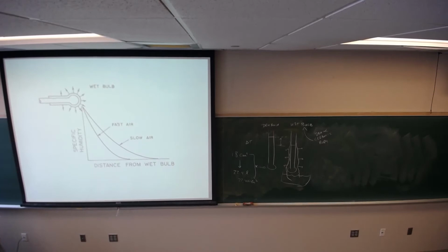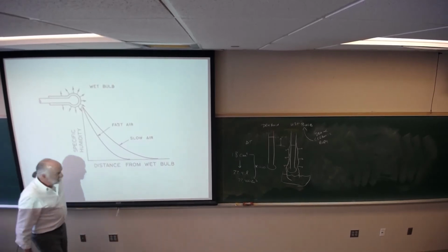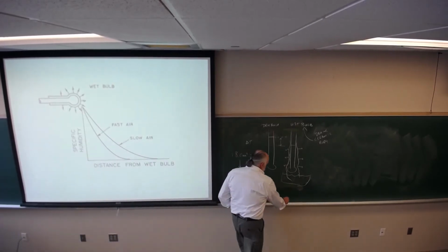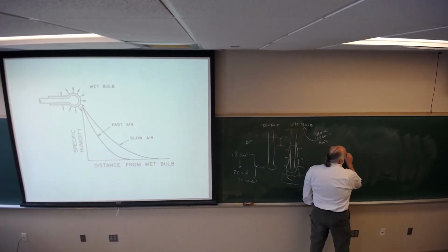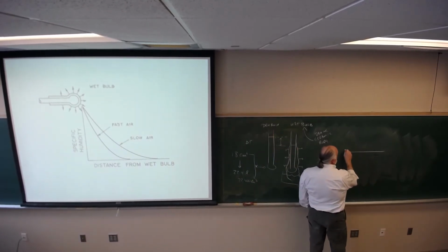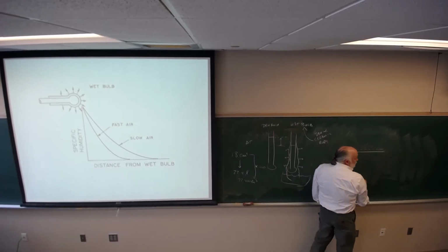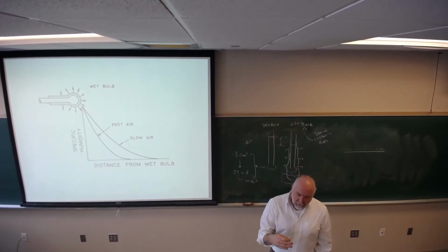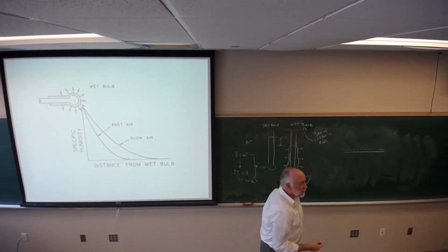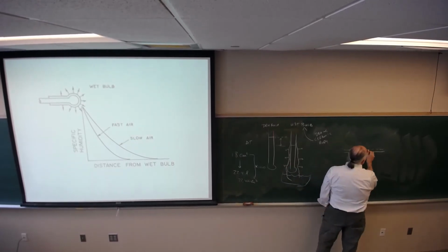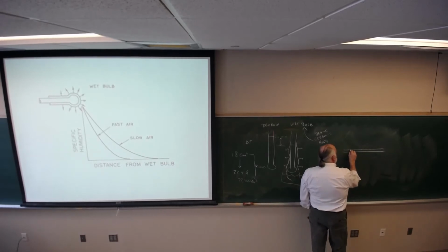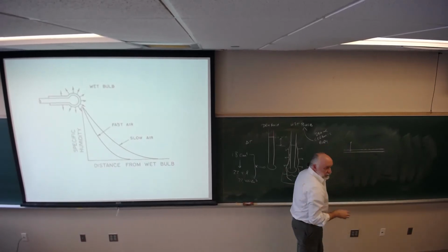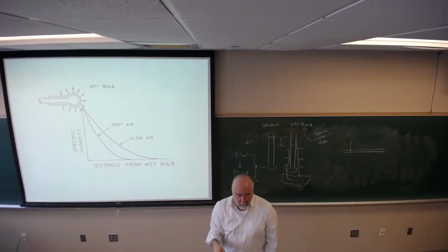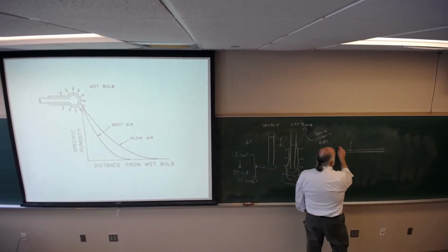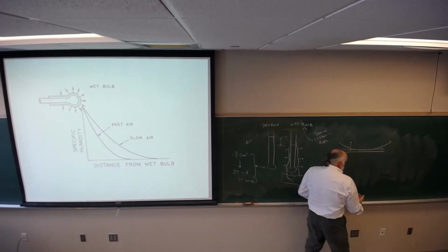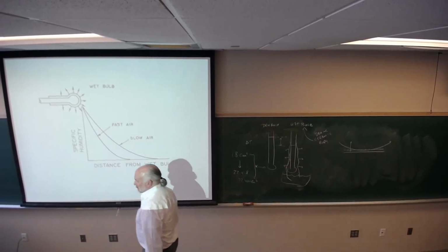And the reason is that on the surface of the free surface, okay, you have a saturated body. You build up a stagnant layer on that surface, okay? And that stagnant layer then slows down the rate at which water gets evaporated. So it's a slow move through here and then faster when it gets out of there. But that slows down, you have a boundary layer effect, what's called. If you blow air over the system, it removes that boundary layer, and then your evaporation rate can improve.